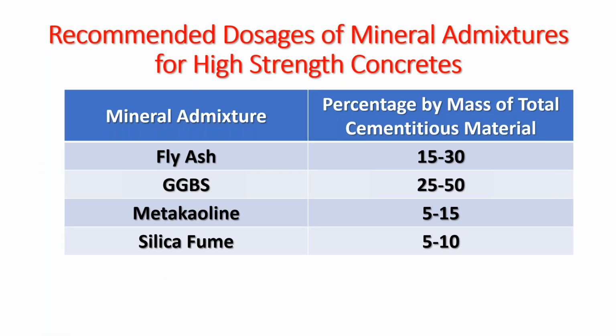And these are all the doses of mineral admixture for high strength concretes. If you are designing high strength concrete, then your fly ash has to be between 15 to 30% in the concrete mix, and GGBS has to be between 25 and 50%, metakaolin 5 to 15%, silica fume 5 to 10%.